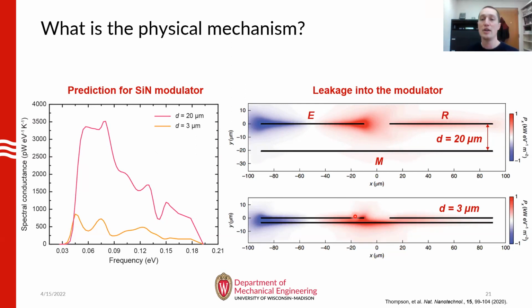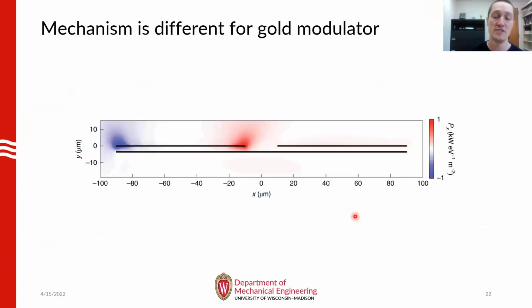What's interesting, though, is that you get a slightly different physical mechanism with the gold-coated modulator, which you can see in this Poynting flux map on this slide. With the gold-coated modulator, it essentially cuts off the mode tails of those guided modes, and those modes are no longer supported by the emitter and receiver. As a result, they essentially scatter into free space, which you can see here. They're scattering above the membranes. But the net result is the same. Less energy is transferred to the receiver, and as a result, the conductance drops.